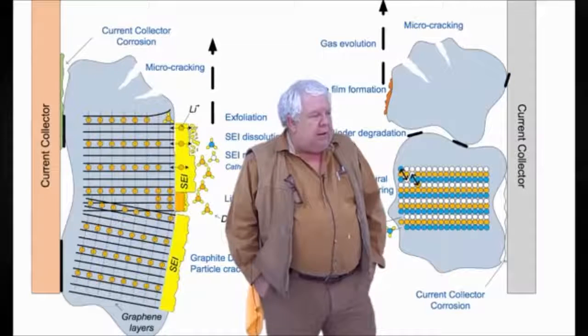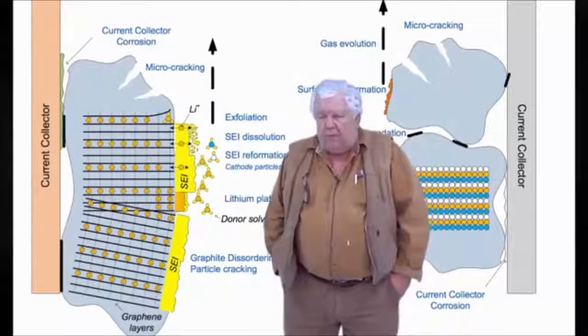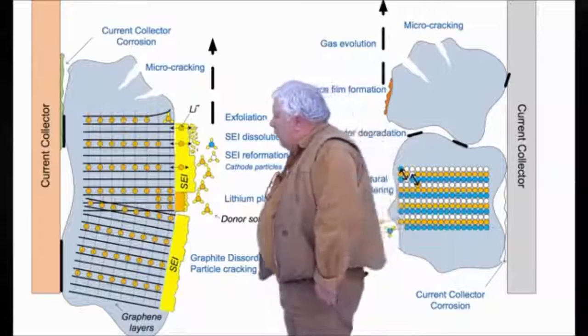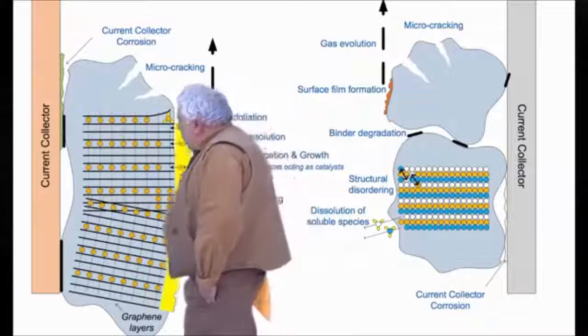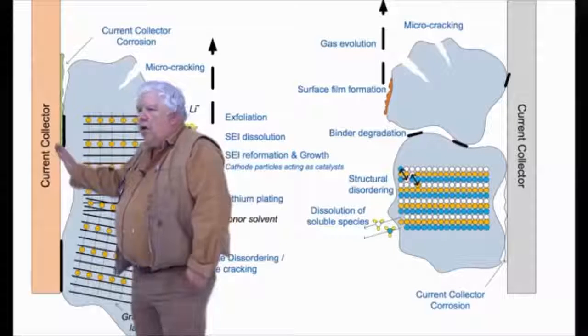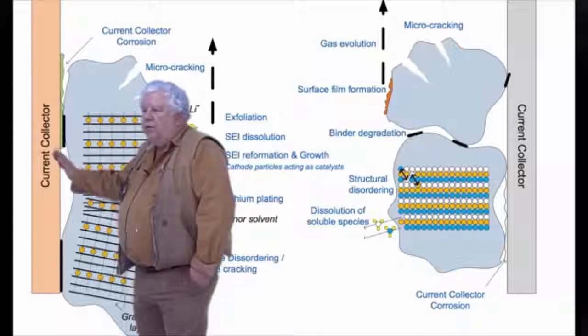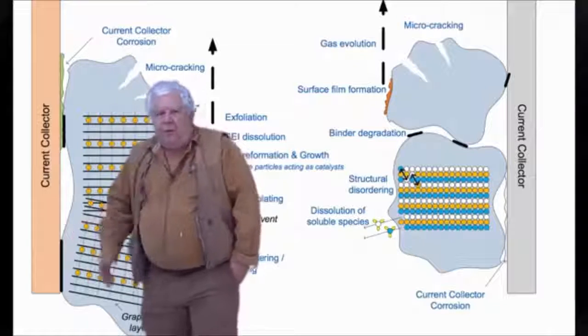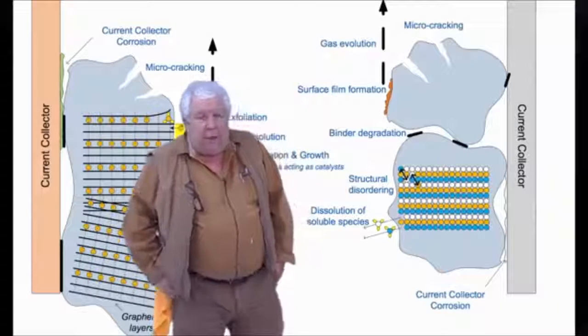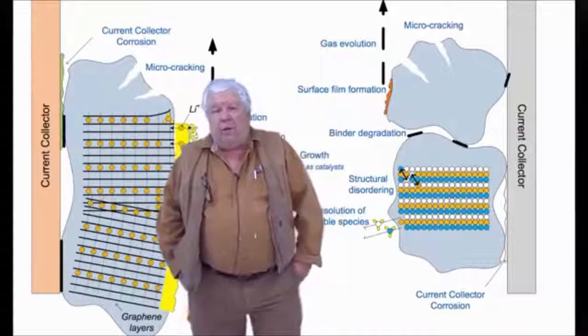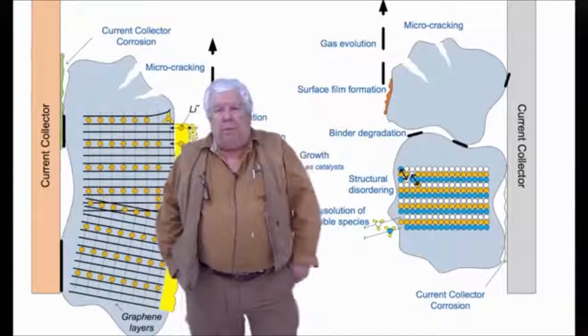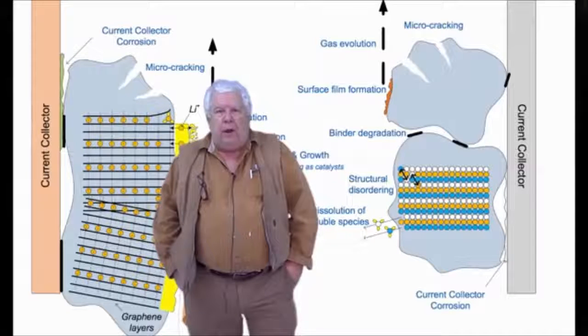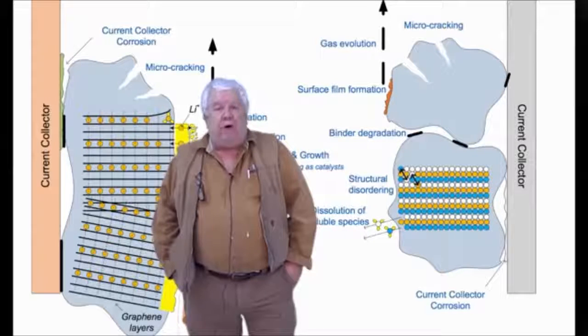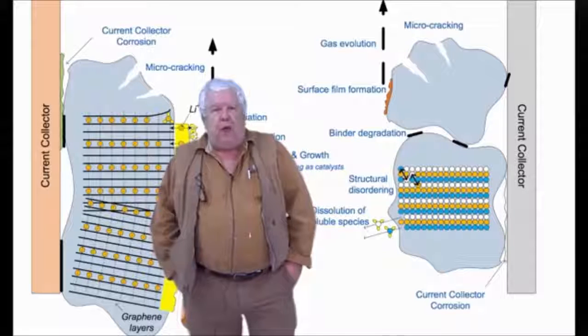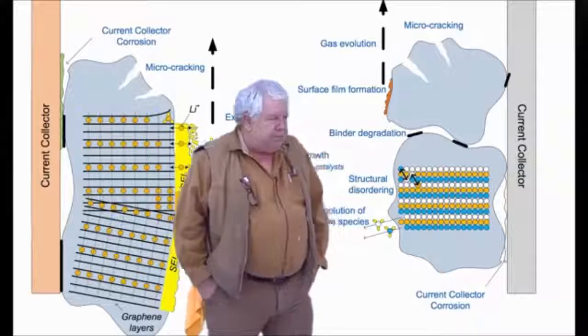Very quickly, and because it's not terribly interesting, you saw in my deconstruct of the over-discharged cell that below a certain potential, the copper on the current collector starts to lose physical integrity, and it leaches through the SEI and into the cell, and it can be deposited anywhere. And it does form dendrites, and it does short your remaining cells, which have no charge on them anyway, but this is why you can't put a charge on them when you get done. You're shorted out by dissolved copper.